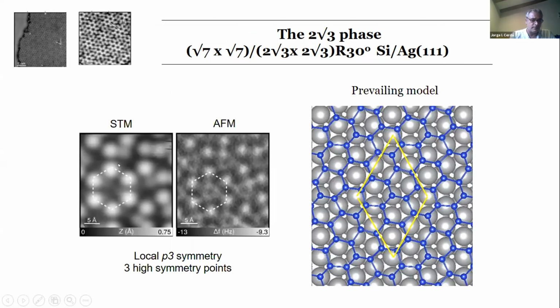These are the STM and AFM images. These are characterized by these rings of bright hexagons, which is just six bumps arranged in a hexagon, and they are very similar again between STM and AFM. All of them show a local P3 symmetry, and actually you can take this symmetry around three points, which would be any of the opposite sides of the hexagon or the center of it. When one is trying to propose a model for this structure, this kind of information is extremely useful. It really shrinks the number of trial models that you need to try.